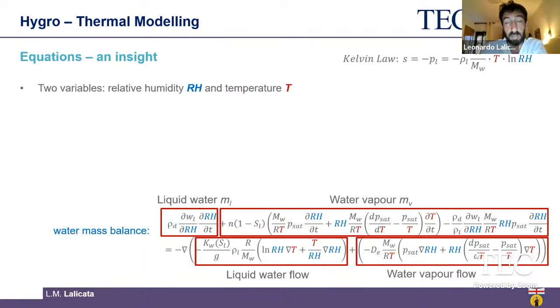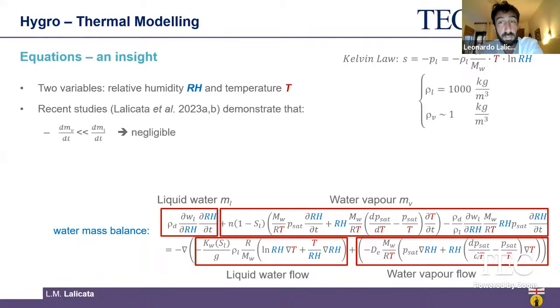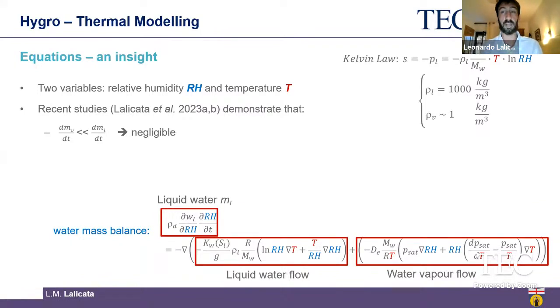So first of all, I have been focusing on the water mass balance, and in particular on the importance of this term here, which is the change in water vapor mass, compared to the change in the liquid water mass. And what we found is that in most applications, the changes in the water vapor mass are much smaller than the changes in the liquid water mass, which means that they are negligible. And if that is true, we can cancel out this term, which really simplifies our life and our equation.